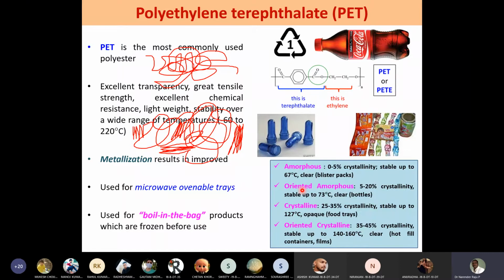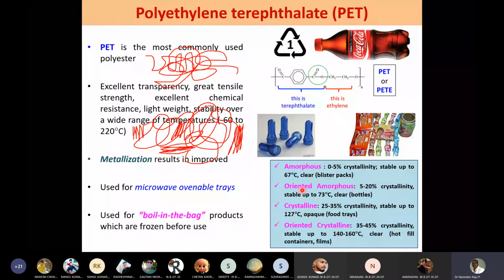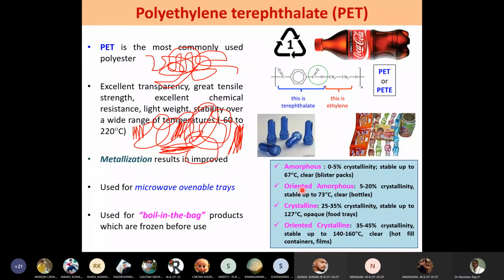It is PET. Technically, it should withstand 121 and above. But warm water or boiling water of nearly 100 degrees centigrade, if you pour in it, it gets shrunken. That means it is losing its heat stability because of the lower crystallinity percentage in it compared to the highly crystalline one. So this has to be remembered.